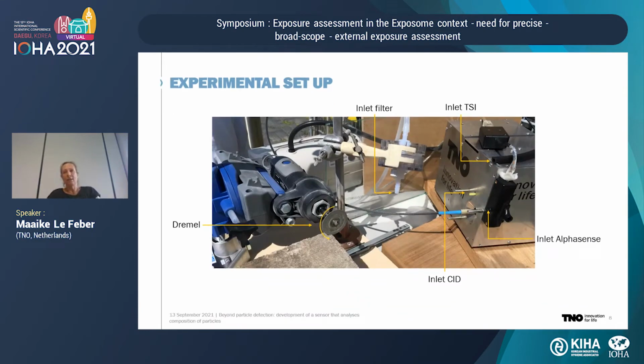Of course, we've tested our system in an experimental setup. Here you see a setup that was used outside our laboratories. So it was done outdoors. And what you see here is a Dremel. It's a grinder which produces the dust. And since there's no gold standard, we use a filter sampling. So the inlet of the filter is signaled in the picture.